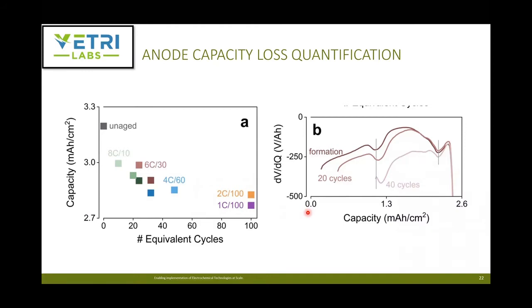This is similar, in the electrochemical literature, to cyclic voltammetry, but in a full cell mode, where we are trying to understand the peaks of the graphite phase. And the distance between these peaks tells you how much capacity you have. And as you see, as you went from the formation to 20 cycles to 40 cycles, the capacity between these two peaks keeps going down. So that's another one that they compared with the half cell study. The benefit of this dV over dQ study is you can do it in a full cell without harvesting the electrode and doing the control study.